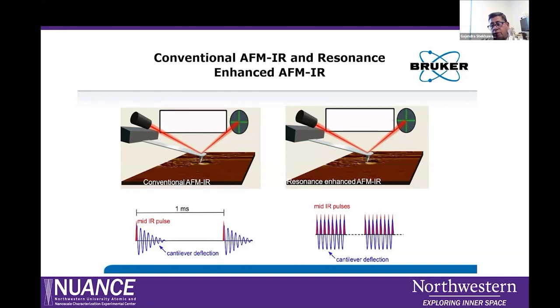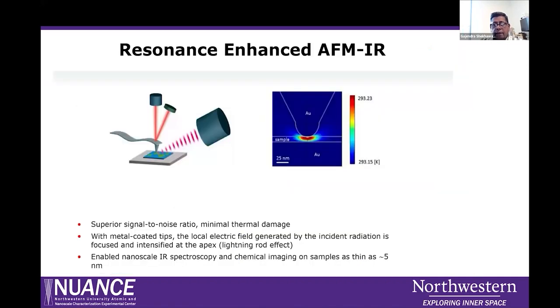It's a non-linear tip-sample interaction, so it's more surface sensitive. If you want the IR signal from the top layers and from the surface, then tapping mode IR is an option for us to go. Then you can see the resonance enhanced AFM-IR signal-to-noise ratio with a metal coated tip. It enhances nanoscale IR spectroscopy and chemical imaging on samples as thin as 5 nanometers.